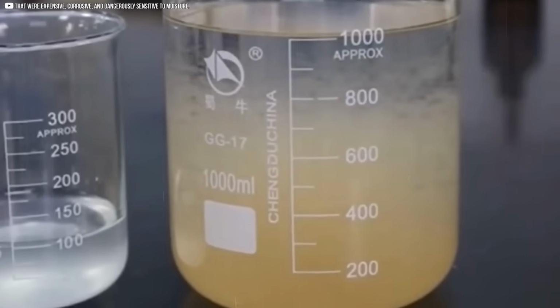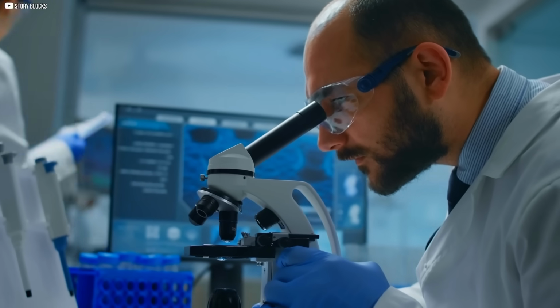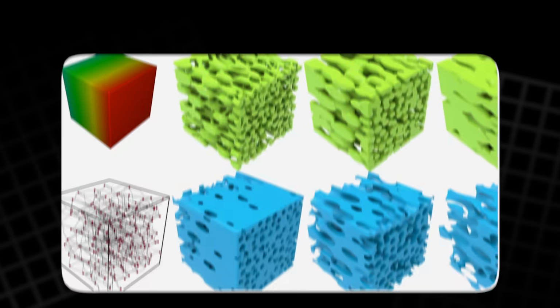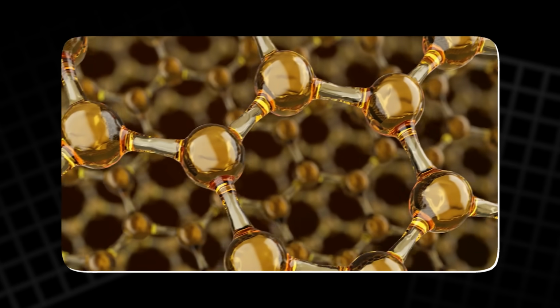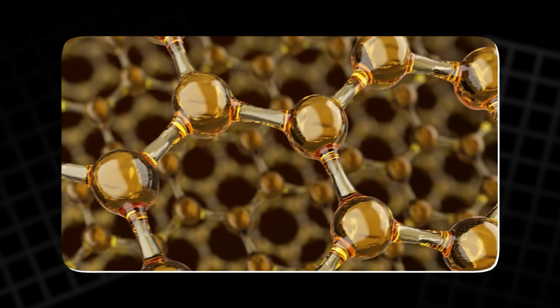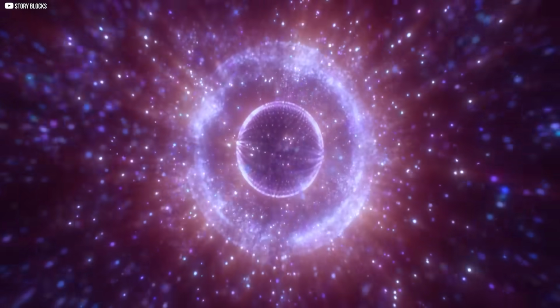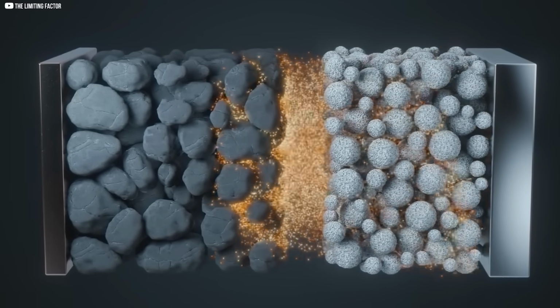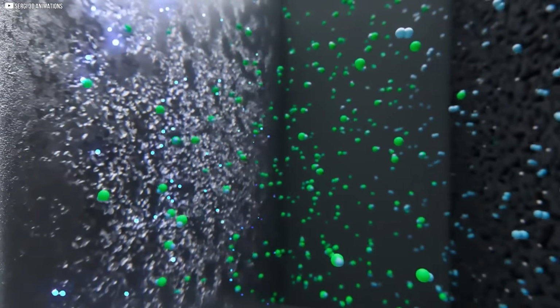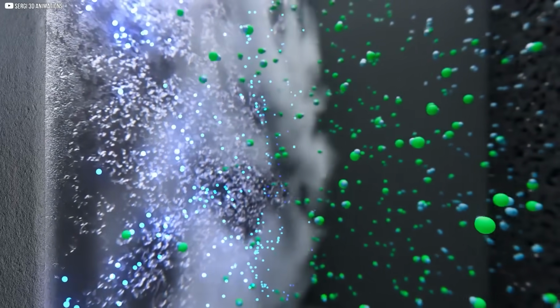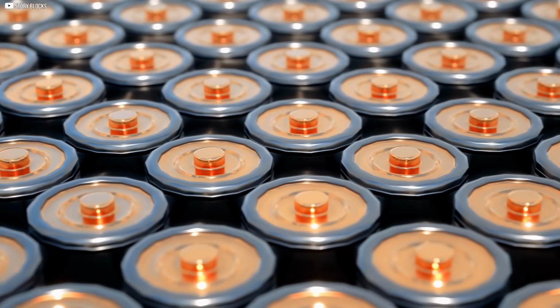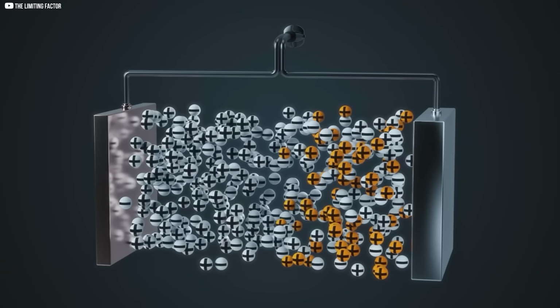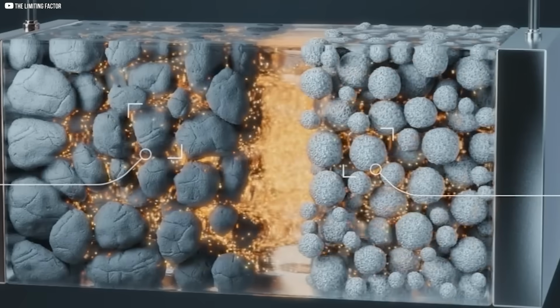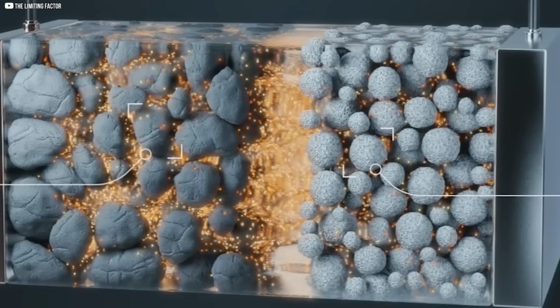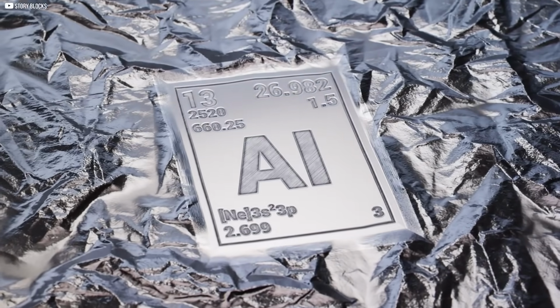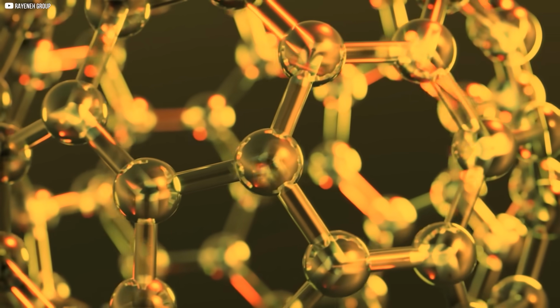At first glance, it was an unlikely candidate, but under a microscope, its structure told a different story, a porous 3D framework that let aluminum ions slip through with far less resistance. This not only boosted conductivity, but also gave the electrolyte a resilience older chemistries lacked. The result was a more stable environment for ions to travel in, one less prone to side reactions that weakened the battery over time. It meant the cells could endure thousands of cycles without the corrosive decay or debris that had doomed earlier prototypes. Stability, once aluminum's greatest weakness, had become its new foundation.